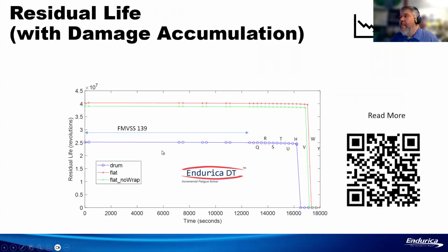And then in the damage tolerant approach, we're computing residual life as a function of time through the 13 steps of the test. And what residual life means is we've got kind of a load case that we can use to measure the life of the tire. So in this case, we've just taken the very first step of the test and we've said, if I took that first step of the test and ran it out till end of life, that's my measure of residual life.